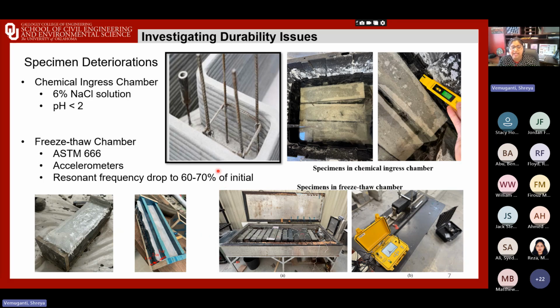So when we looked at those specimens after the typical fabrication and the concrete curing, we went ahead to do some exposure studies for durability. So here we see a standard chemical ingress chamber with 6% sodium chloride solution. We've maintained every day a pH to be less than 2. And when we come to the freeze-thaw chamber here, we've subjected these interfaces to freeze and thaw environments as well.